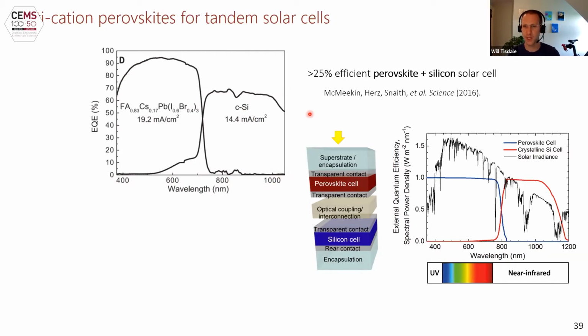spectrum. So Henry Snaith and co-workers made a nice publication, a proof of principle device a few years back. And the real interesting thing here is that the perovskite that they made, when they made to tune the band gap bluer, you need to have an alloy of iodide and bromide to shift the band gap to the correct position. And that when you do that, the best performing perovskite formulations have a mixture of different cations, in this case, some formamidinium and cesium.